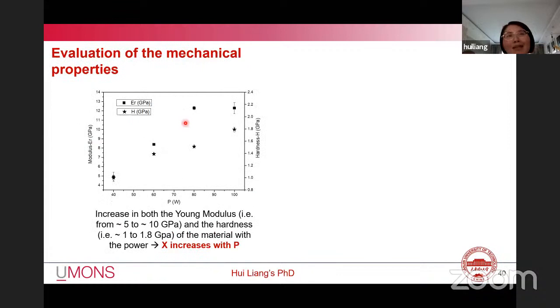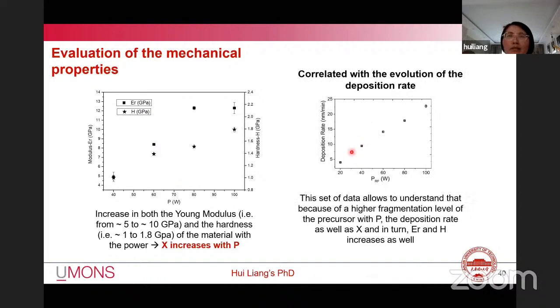The evolution of the mechanical properties, as shown in the figure on the left: the hardness and the Young's modulus of the coating increased with the RF power increasing, and the change trend is the same. It can be explained that the mechanical properties are also determined by the degree of cross-linking polymerization. Thus, the higher the power, the higher the degree of cross-linking polymerization. The figure on the right shows the change of deposition rate with the work power. With the increase of power, the deposition rate of the CH coating increased linearly from 5 nanometers per minute to 22.7 nanometers per minute, which can be explained as increased power leading to more particle collisions.